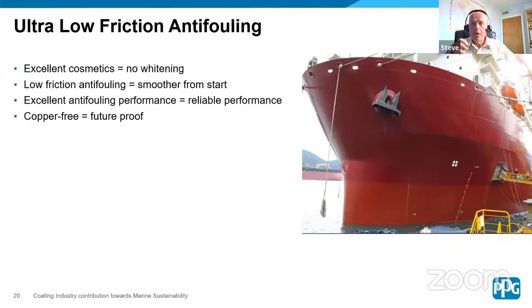Another benefit of the copper-free technology is you don't have this changing colour. Cuprous oxide is not only a biocide, but it's also a pigment. So you start off with a rich red-brown colour, and then shortly afterwards, as that copper migrates out of the film, it starts to turn pink. As the copper leaves the coating, the colour deteriorates. And we don't see that, so we get better cosmetics with this copper-free technology.